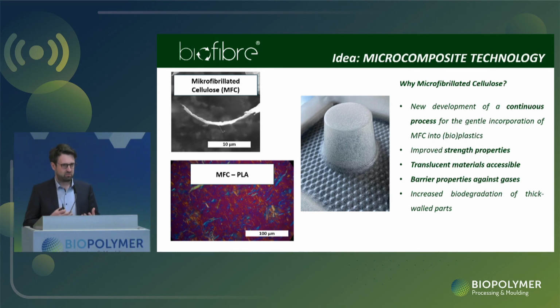So back 4 years ago, we were frequently asked for applications that require thin-walled injection molding, for example. And then we came to a level where we could not go below, for example, 500 micron or 0.5 millimeter in wall thickness. And another aspect was that the fibers that are bigger in size, or macro scale, are blatantly visible, and for example, for film application, this is not desired. Clients desire, for example, translucent products. So we accessed the market of microfibrillated cellulose, and looked at how to combine those micro-scale fibers into bioplastic binder systems, but as well other binder systems, natural binder systems.